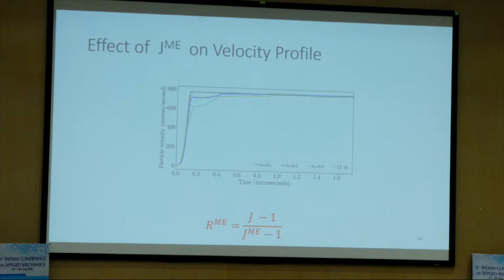When you put them under compression, what happens? Locally at the flat tip, the stress is not compressive. It is tensile. So the applied mechanics people, see, this is an applied mechanics conference, theoretically said, hey, by the way, brittle materials will fail. Bulk modulus will degrade under compression, whereas in an equation of state under compression, bulk modulus increases.